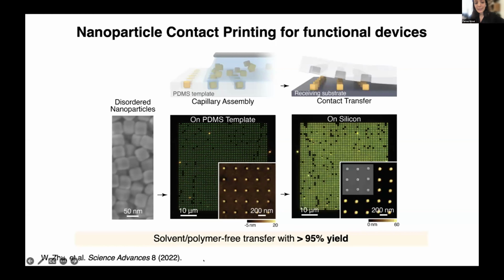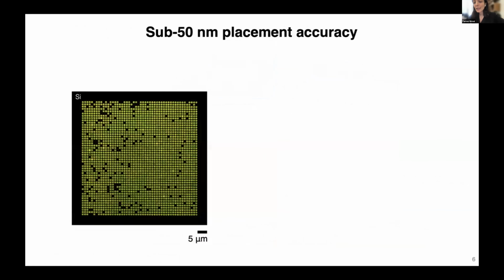So in this case, we take the nanoparticles that are assembled onto a PDMS template, and you can see they're printed onto a silicon surface with more than 95% yield. And again, in this case, a combination of TEM, AFM, and more high throughput optical and dark field imaging has been used to characterize the steps.